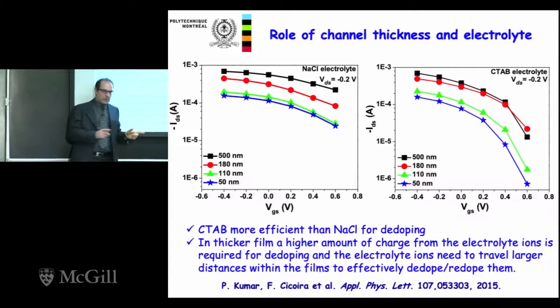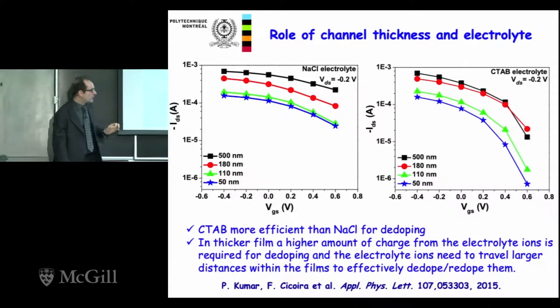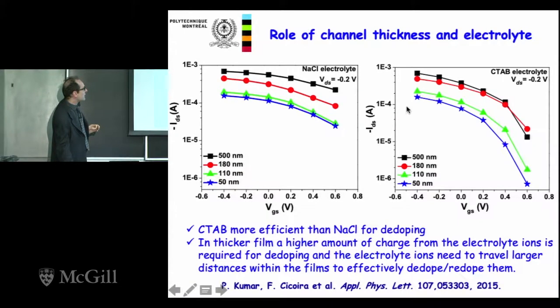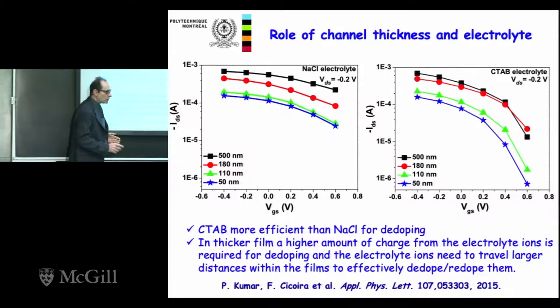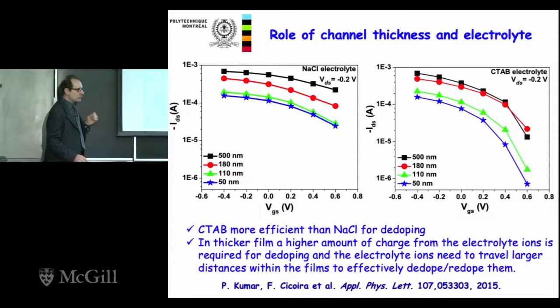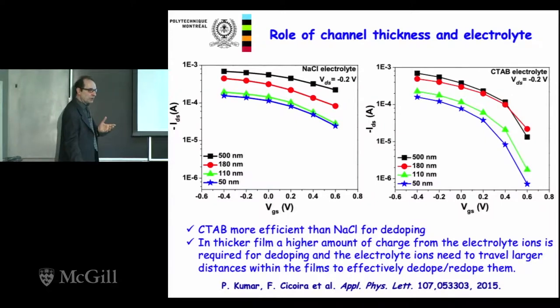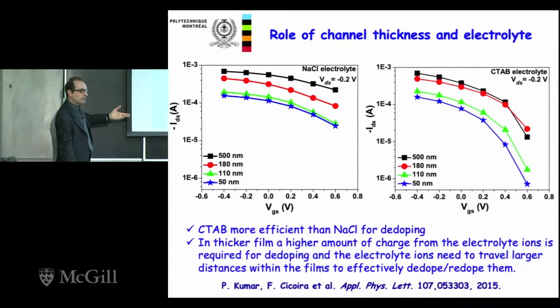These plots also tell you another thing. I don't know if you can follow that, but you can see that our transistor, if we don't apply any voltage, is in the on state. So you have to apply voltage to switch the transistor off. And these kinds of transistors are called depletion type transistors. So they work in depletion mode in the sense that you apply voltage to switch them off. This is because we start from a highly conductive material and we decrease its conductivity by applying the voltage.